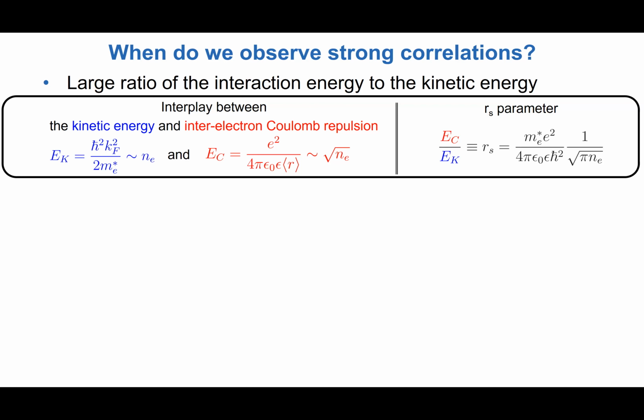The higher the effective mass, the higher the r_s parameter is, and the smaller the dielectric screening is, again, the larger the r_s parameter will be. And of course, this doesn't mean that we can just lower the electron density arbitrarily and then we will have strong correlations, because there is always practically a limit coming from the disorder in the system.